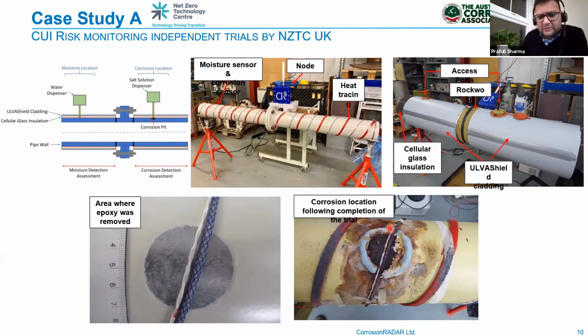So you can see over time the corrosion location, where the water was. You can really see the corrosion happen on the pipe, but there is also corrosion on the sensor, because the corrosion sensor is a coupon.